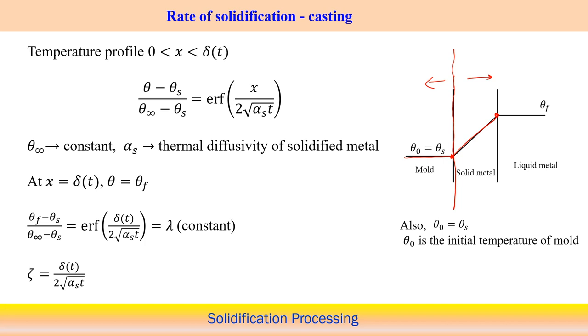So there is no temperature gradient along the mold surface, which we are assuming here. Now the temperature profile between 0 and delta t, at this distance, is given by: theta minus theta s divided by theta infinity minus theta s equals error function of x over twice root of alpha s into t. Here alpha s is the thermal diffusivity of the solidified metal, and theta s is the temperature on the surface. At this point the temperature equals theta s, and theta is the variable, but theta infinity is a constant and theta s in this particular case is a constant.